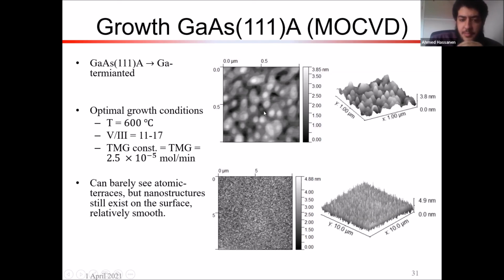And what we got was, you can barely see atomic terraces. It's relatively smooth, but you still get all these nanometer bumps, as you can see here. And when you zoom out, you can see that it's relatively uniform, but still quite bumpy.